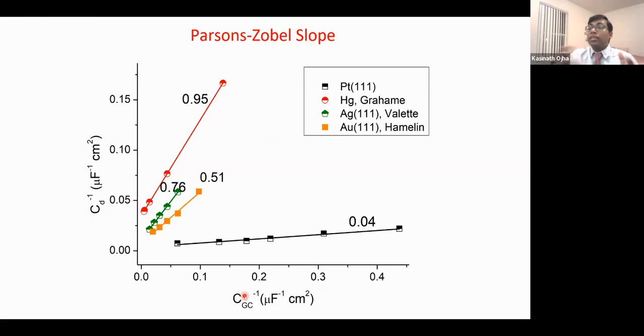Now, if both experimental and calculated capacitance are the same, you're going to have a linear curve with a slope of 1. And if you remember the first experimental data on the double layer structure, that's Grahame on mercury. That was quite ideal. You have a slope of 0.95. It's very close to 1. Perfect. People believe it and it's really nice.